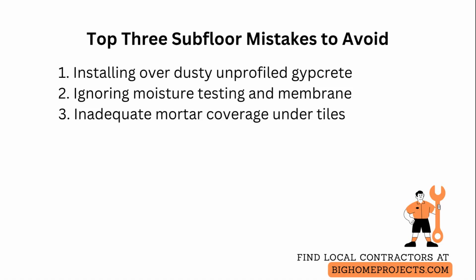A third problem is inadequate mortar coverage under large format tile, leading to lippage and cracking. The solution is to back butter large tiles, use a trowel notch size appropriate to the tile thickness, and perform spot checks by lifting random tiles after they are bedded to verify full contact.